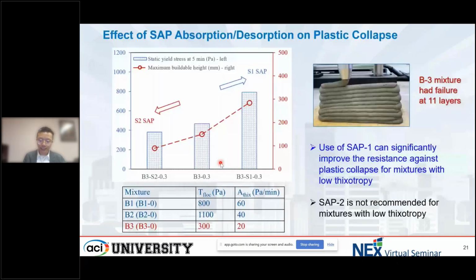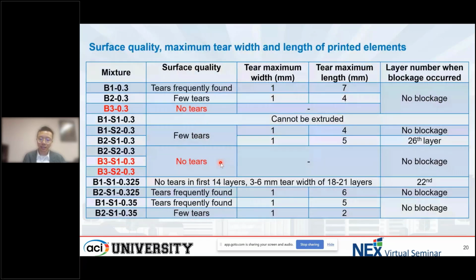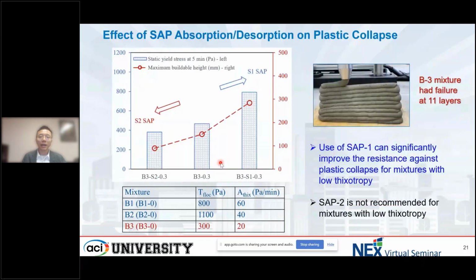But does that mean all SAP can be used in binder 3? The answer is no. The binder 3 mixture had very low thixotropy, so the failure happened very early, at around 11 layers. And when we use SAP2 in this mixture, it further reduced the thixotropy, and the plastic collapse happened even earlier. It means that SAP2 is not recommended for mixtures with low thixotropy. But when we use SAP1, it can significantly increase the thixotropy value and then improve the resistance against plastic collapse.